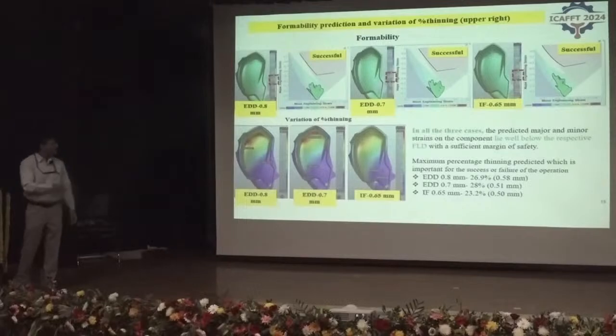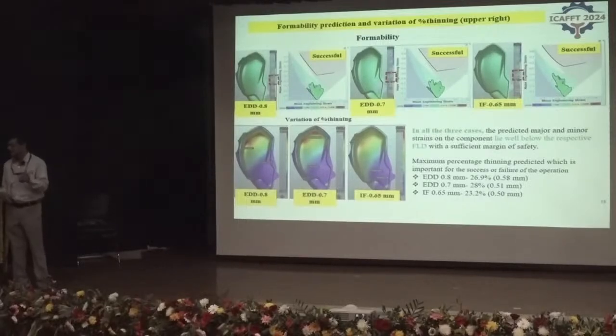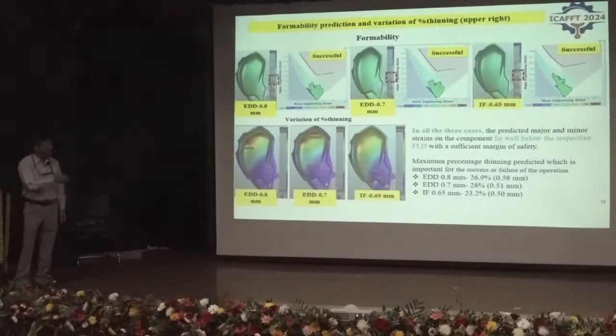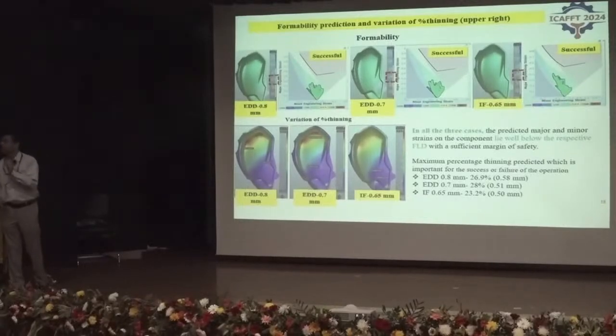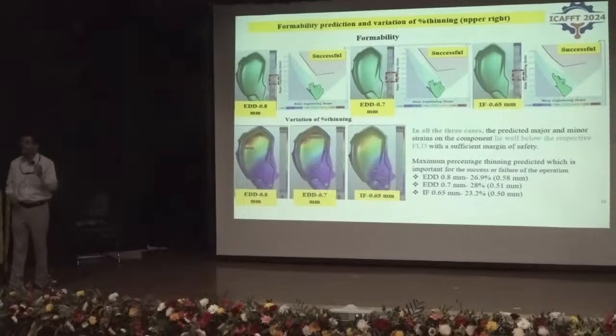And when we changed the grade to IF steel, we have seen, by doing a large number of simulations, that the sheet thickness can be further reduced to 0.65 mm. So that would reduce the weight even more. But it would slightly cost more because IF steel is costlier than EDD steel. So we need to see where the balance is. Okay, and so you can see the maximum thinning in different materials, about 27%, 28%, and 23%.